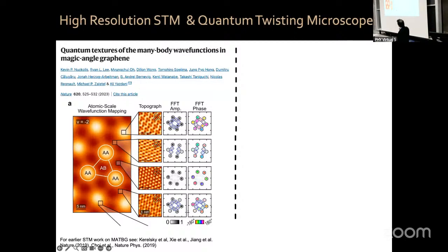One of the nicest papers, two years ago, is this work by the group of Ali Yazdani, where they used STM to image the Moiré pattern—here are scanning tunneling microscopy images showing the AA sites. They looked over a large area, large by STM standards, imaging these Moiré patterns with atomic scale resolution, so that if you zoom in, you can see the actual carbon lattice.